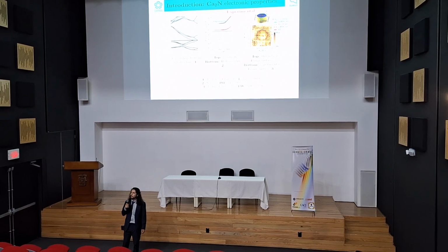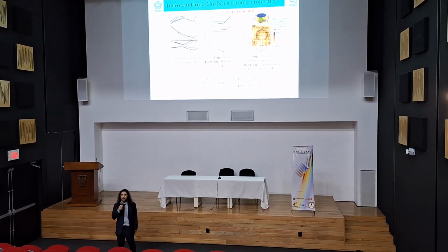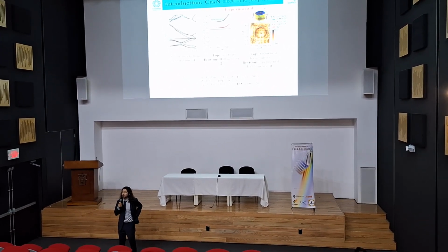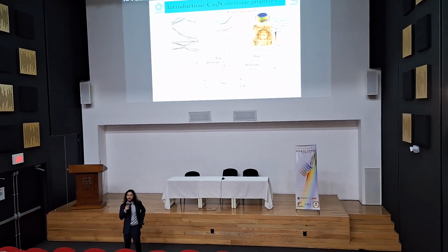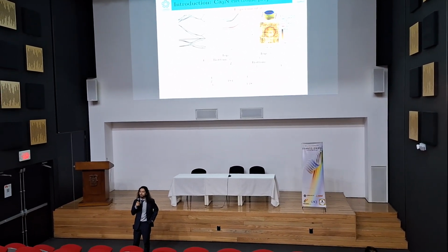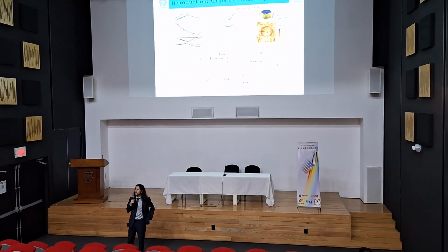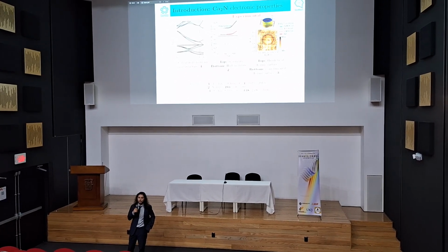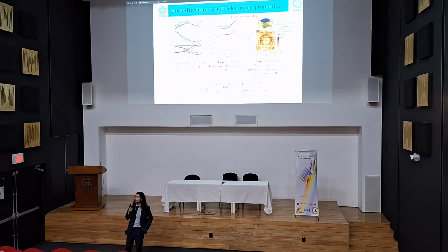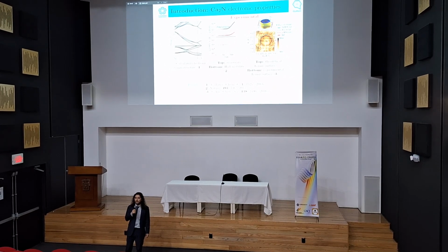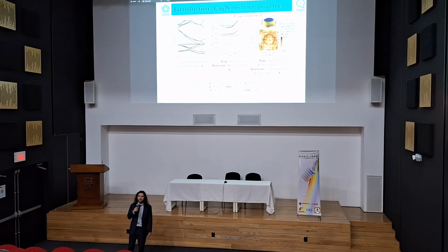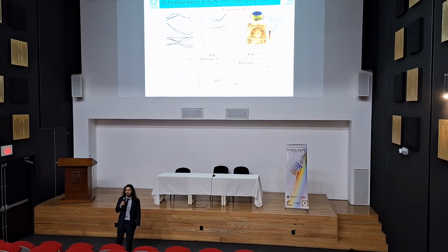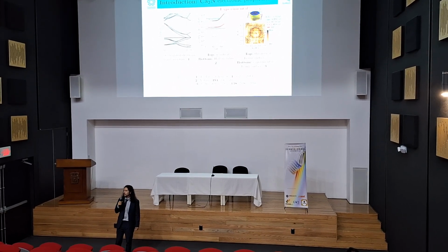Later, experimental transport measurements on both polycrystalline and single crystal samples showed that the material has metallic behavior and high electrical mobility. 3 years later, experimental measurements of the Fermi surface showed a closed orbit, which is typical of conductive materials. Next, please.